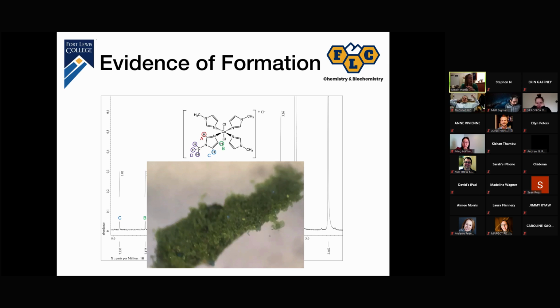And so we've also tried recrystallizing this. We've tried different purification methods, and we've sent it off for elemental analysis. And this is another one that's kind of going back to look like imidazole. The elemental analysis isn't matching the predicted structure with the high degree of symmetry with 4 1-methylimidazole ligands attached to the cobalt center and the trans-chloro groups. Our elemental analysis is actually matching much more closely that we have 3 methylimidazoles attached to the cobalt metal center. And so we're still investigating and trying to find the right conditions to have very pure forms of this product to figure out exactly what's going on.